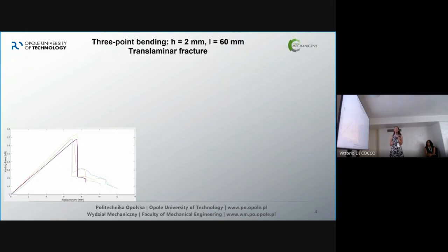Okay. So the first material was the three-point bending of the very thin specimen with 2 millimeters. And I was sure that I'm going to obtain pure crack due to normal strain. I analyzed 5 specimens for each dimension, so we have here the graph, and the purple dotted line is in here, which I'm going to show you now.